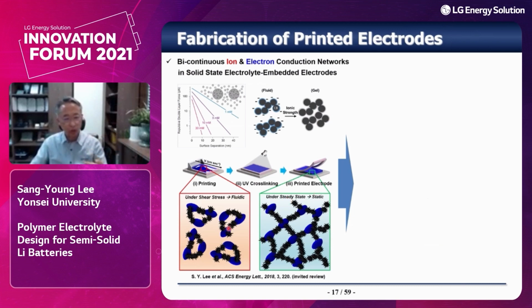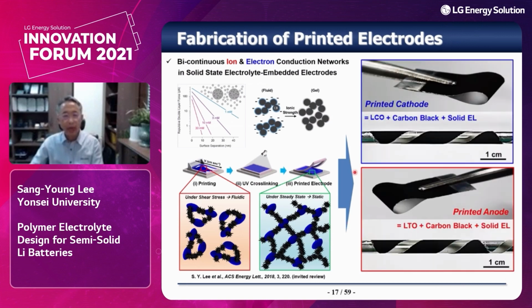Also during the fabrication process, we needed to be careful about how to control the interconnected network structure inside the printed electrode. Anyway, we have obtained the printed cathode and printed anode. As a first trial, we have used lithium cobalt oxide as a cathode and lithium titanium oxide as an anode. Here, the solid-state electrolyte was already embedded.